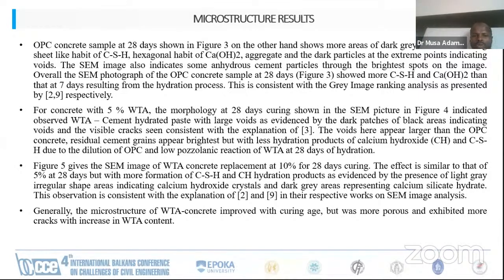Then figure 5 also gives the SEM image of WTA concrete with 10% at 28 days curing. The effect is similar to that of 5% at 28 days, but with more formation of CSH and CH hydration product, as evidenced by the presence of light gray irregular shaped areas indicating calcium hydroxide crystals and dark gray areas representing calcium silicate hydrate. This observation is consistent with the explanation of references 2 and 9 in the respective work.